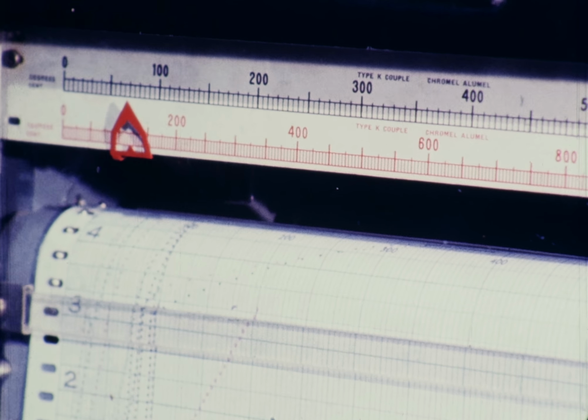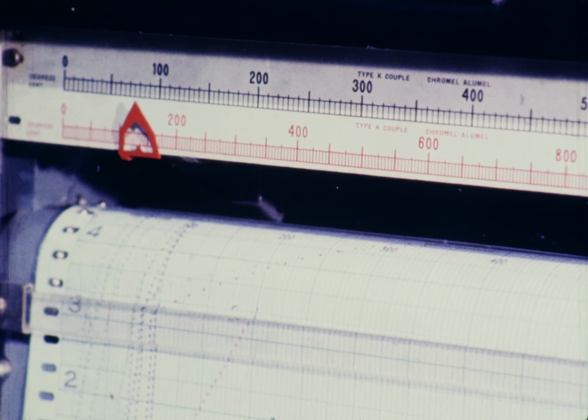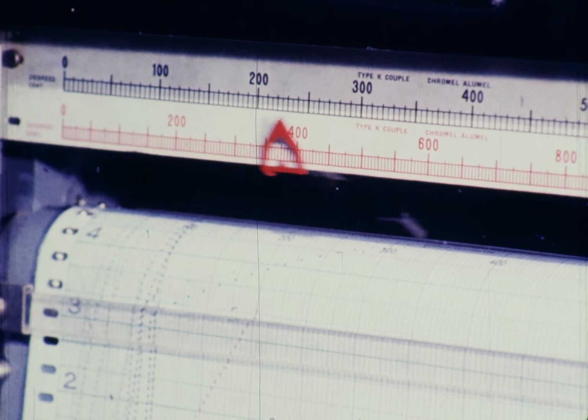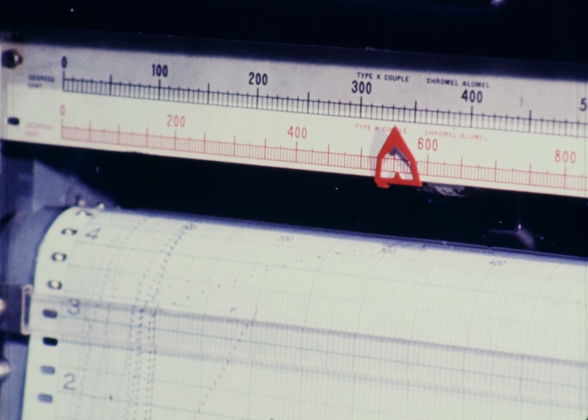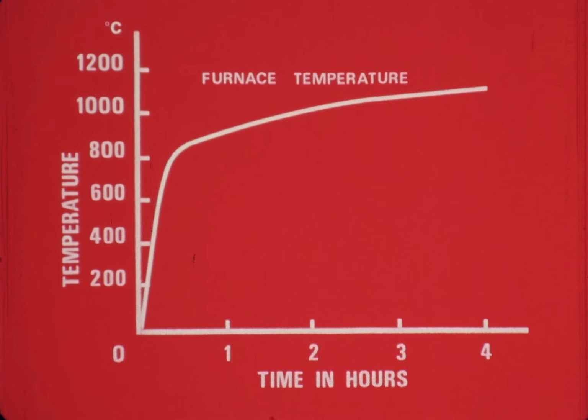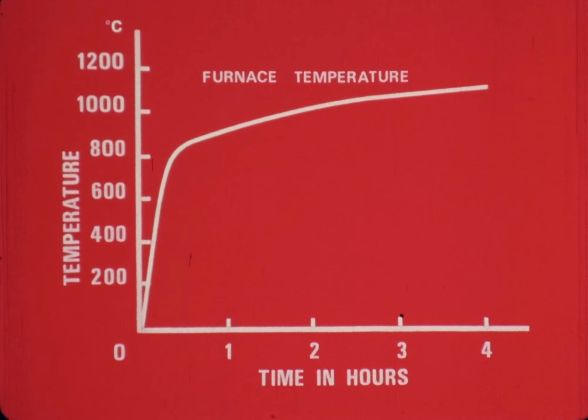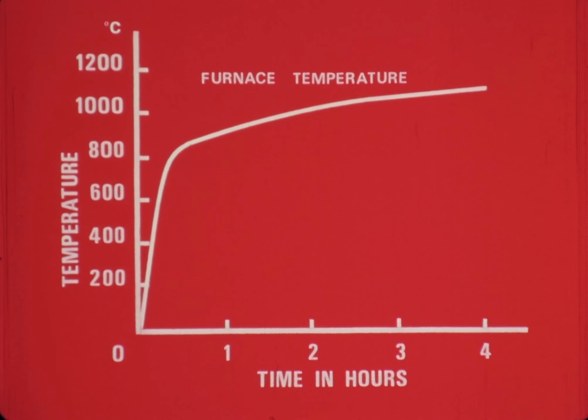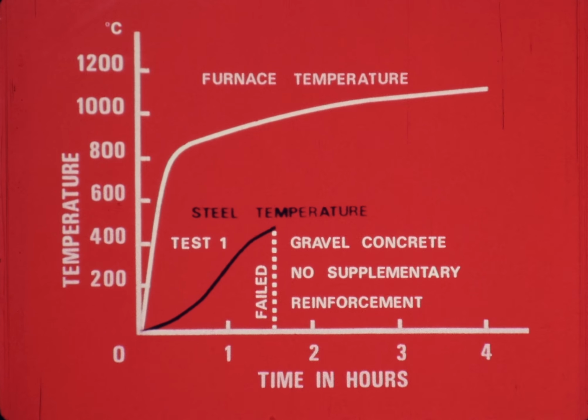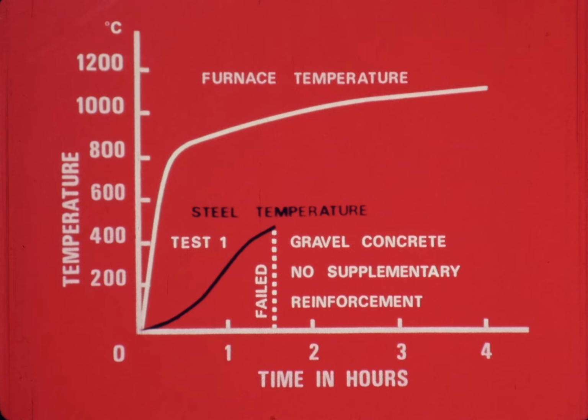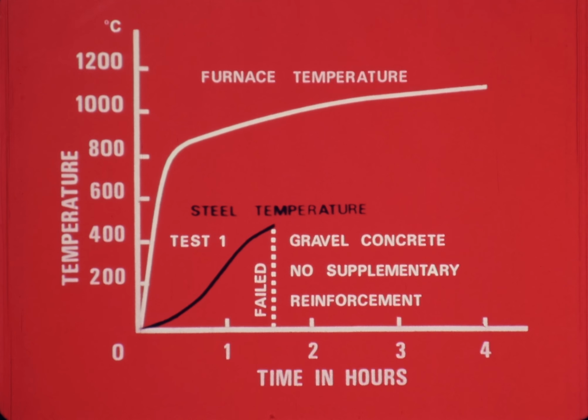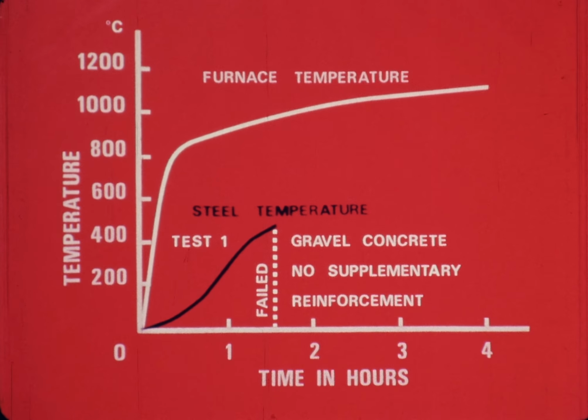The time temperature records show the degree of protection given to the steel by each form of construction. Let's compare the records for the 3 tests we've just seen. This curve shows the furnace temperature, which rose at the standard rate in each test. The black curves represent the steel temperature. In the first test, the steel had a cover of 2.5 inches of gravel concrete. This spalled away fairly quickly, so that the steel temperature rose to 400 degrees in only an hour and a quarter, and the beam failed after an hour and a half.